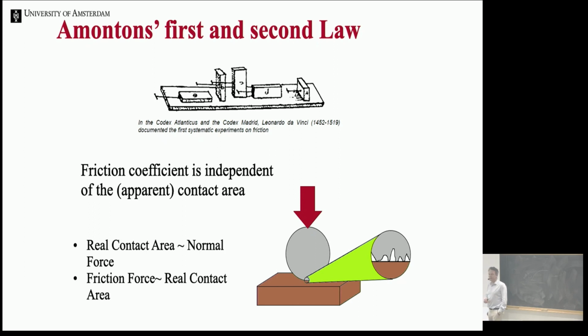And so if you zoom in on the contact, you will see that only a very small fraction of the two surfaces actually touch each other. And so Amontons proposed that if I push twice as hard on this microscopic contact, I might make twice as much surface. And then if, and only if, the friction force is proportional to that area of real contact, the contact area drops out of the friction coefficient. And then we have an explanation for Da Vinci's measurement, but also for the everyday engineering observation that you don't need to specify the shape or even the surface properties of two sliding objects to get a friction coefficient.